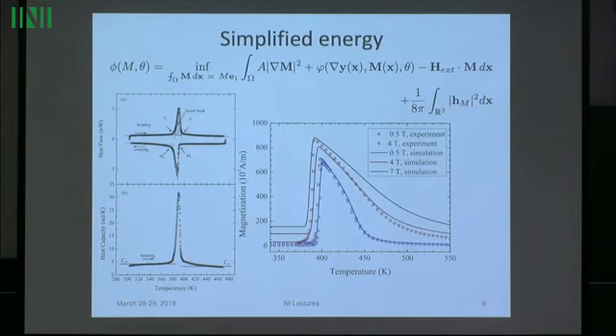So when you apply a field, let's see, the blue one. Yeah. In this particular material, it can happen either way. But in this particular material, if you put a magnetic field on, it lowers the transformation temperature, as indicated by this graph. And from this information, and also these magnetization curves I mentioned, you can develop a free energy in a scalar model. Most simple, all the space dependence is out, and it's just a scalar model where the free energy depends on magnetization and temperature. Magnetization is some average magnetization in a certain direction, the relevant direction for this energy conversion. Okay.